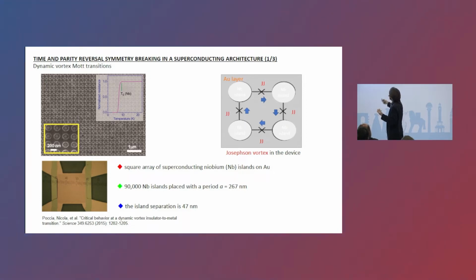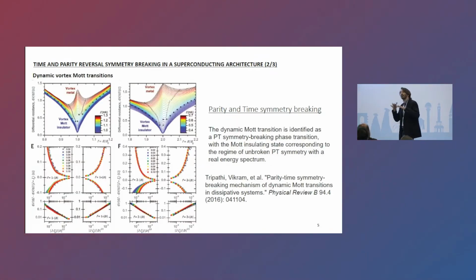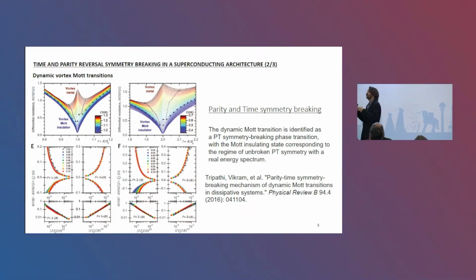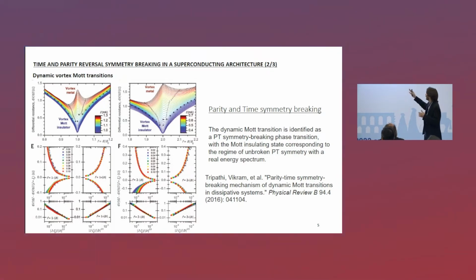Now, you can think about this Josephson vortex to some extent also like atoms in an ultra-cold atom optical lattice. If you apply a current, this system goes into a non-equilibrium state. Depending on the current and the magnetic field that you apply, you can move the system from a vortex Mott insulating state. There you see the differential resistance and the filling factor on the x-axis, which tells you how many Josephson vortices, in which kind of crystallographic configuration, are organized in your superconducting array. In this case, there is one Josephson vortex for each plaquette of superconducting islands.